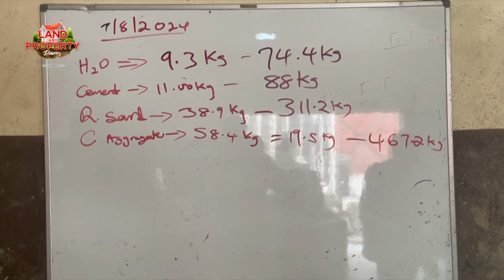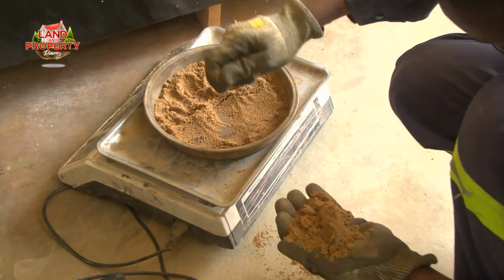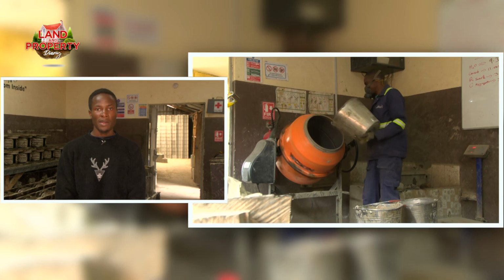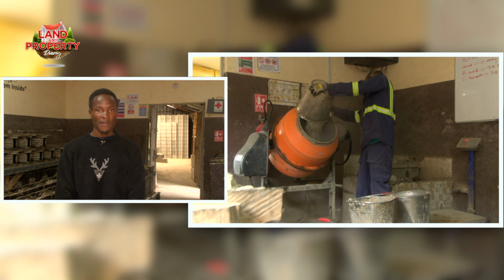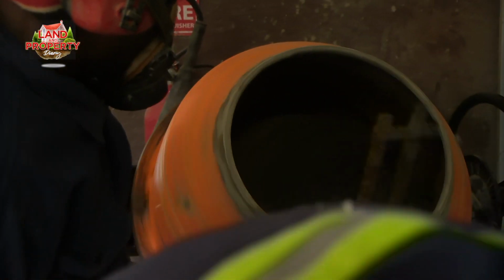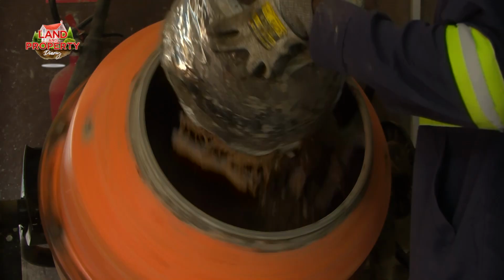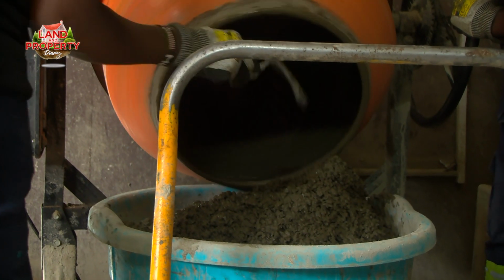And then the procedure itself also involves distinct steps or stages that are to be followed by the people who are doing the mixing. That is, you have to first pour water in the mixer, then subsequently add cement to initialize the hydration process of cement, and then after a few seconds you pour in the coarse aggregate, and then consequently add the river sand. Practically it takes around 3 minutes to do the actual mixing and to achieve the desired consistency.